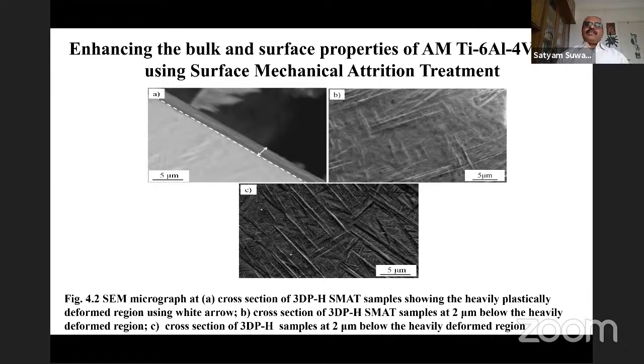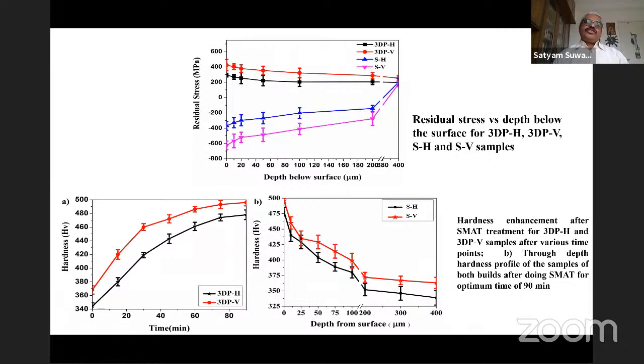So as I said, we all started our work with severe plastic deformation. So severe plastic deformation, like surface mechanical attrition treatment, has been found very effective for enhancing the properties of Ti-6-4, because it closes the surface porosity, generates compressive residual stresses, and eventually leads to a very optimal fatigue life of these components. Residual stresses, we can see that just by doing this post-processing, it totally changes from tensile to compressive nature, and its attributes are seen in all the properties.